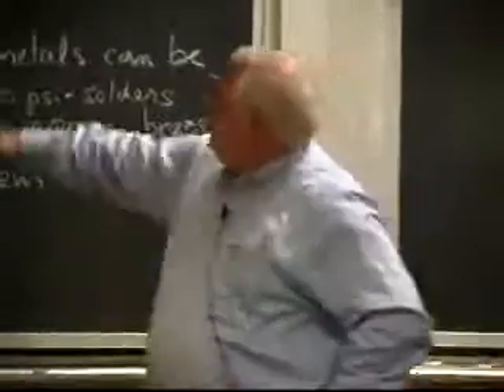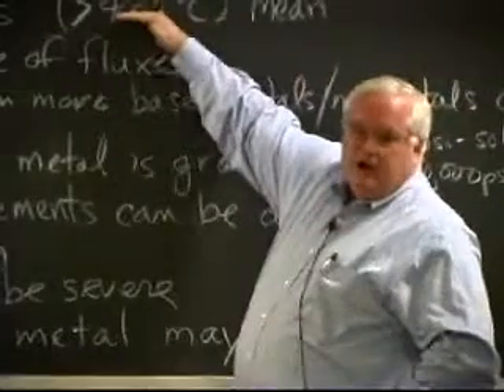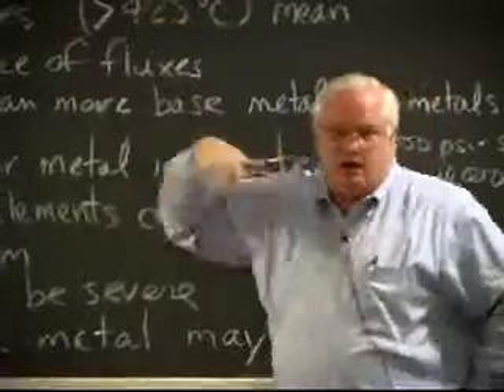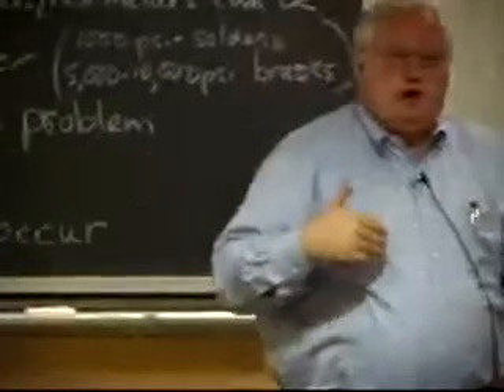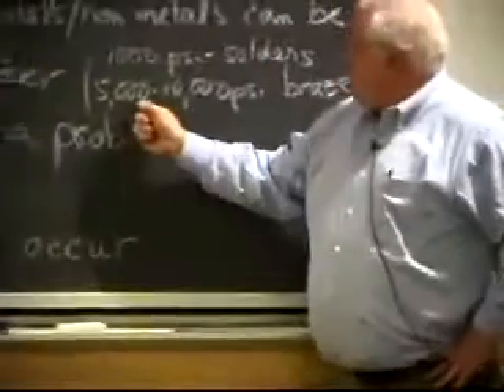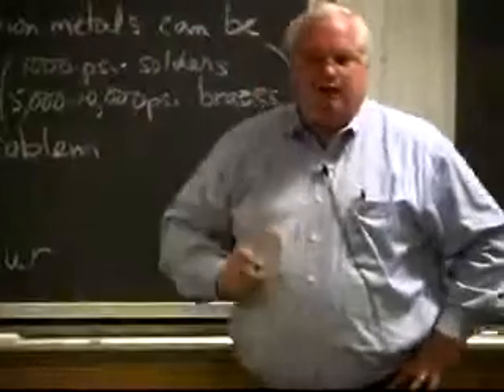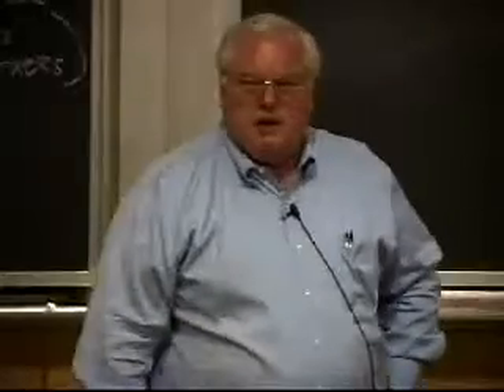Brazes, on the other hand, since you're at above 425 C and you add 275 to that, you get 700, and then you talk about 300, you're below 6/10 of the absolute melting point in most cases. And so you're not really in the creep regime for the braze alloy, and at room temperature you can get 5,000 to 10,000 psi. To compare those numbers with adhesives, typically with adhesives you may only get 100 to 500 psi as a bond strength. Remember, adhesives, we said you need lots of surface area. That's because the adhesive strength is not so great.